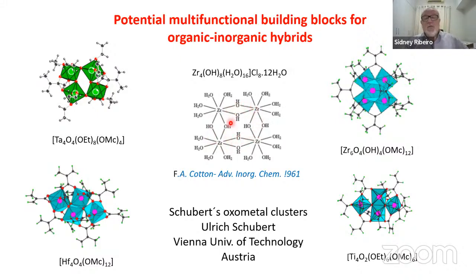famous inorganic chemistry book from '61. So this is the cluster that we have in aqueous solution of zirconium 4+. And this is the formula that we have for this species. The size of this colloidal particle is around 2 nanometers. This is the size of what we call today nanoparticle. In '61, this was not so interesting. And after that, I can mention the work of Professor Schubert in Austria. And these are some of the building blocks that he was able to prepare with tantalum, with hafnium, titanium, zirconium. This is a very beautiful work of Professor Schubert, very well known in the area.